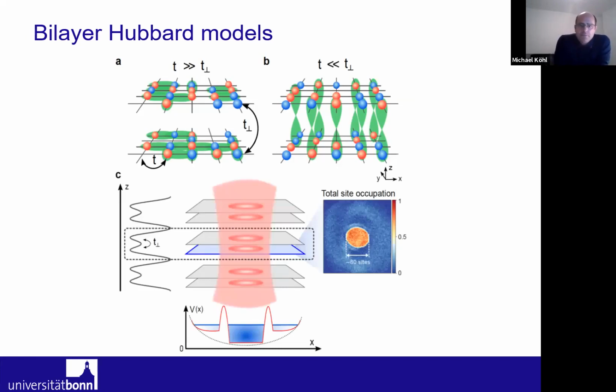So the experiment roughly looks the following. We now have these coupled planes, this one, this one, this one, this one. And in order to increase our chances of observing this, we've additionally made flat potentials in these layers. So we use a DMD to compensate the harmonic trapping potential. We use then some boundaries here where we cut off the density. So we basically create a flat bottom bucket where we collect the atoms, and then some atoms spill over into these entropy reservoirs here. And then we get a very cold and dense sample at the center, which spans around 80 lattice sites approximately. And here you see an in situ image of this. So you see the dense core, and then some atoms scattered around here in very low density regions. And we hope that they also contribute to reaching low temperatures, because they can take up some of the entropy that is squeezed out from the core system.